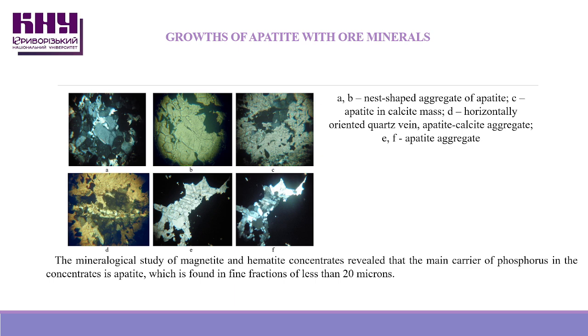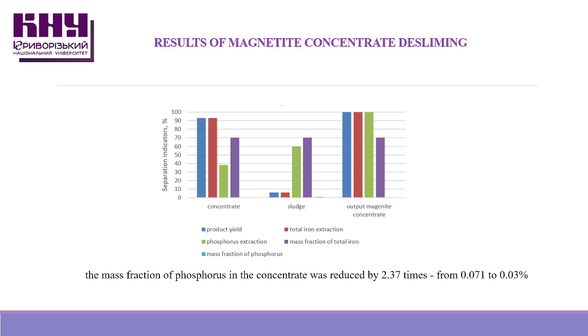As a result of mineralogical examination of magnetite and hematite concentrate, it was determined that the main carrier of phosphorus in concentrate is apatite. The grain size of apatite varies widely from units of micrometers to tenths of a millimeter. Apatite is concentrated in a fine fraction of less than 20 microns. Based on the analysis of the results of examining the material composition, chemical and mineralogical properties of magnetite and hematite concentrates and the properties of apatite, it was concluded that it is advisable to conduct desliming of magnetite concentrates and